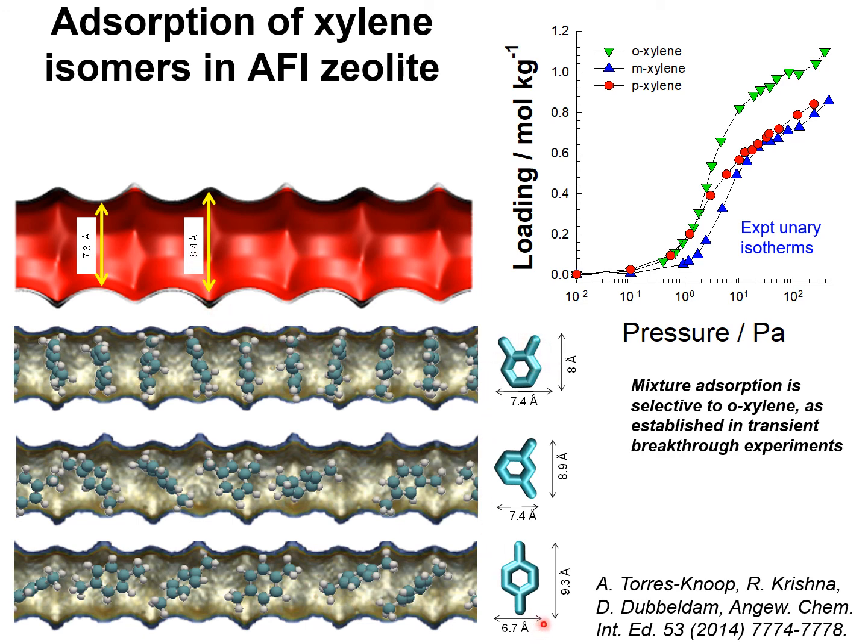On examination of the molecular dimensions of orthoxylene, metaxylene, and paraxylene, it is possible to see that orthoxylene can be located vertically within the grooves in a face-to-face packing that results in footprints that are very small.